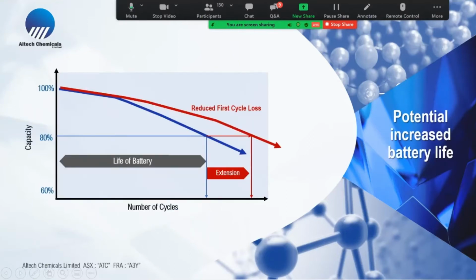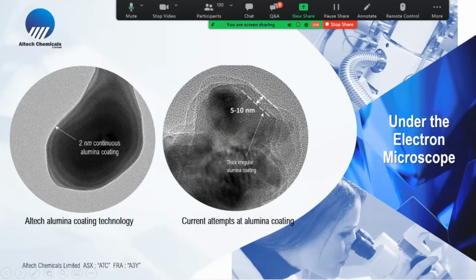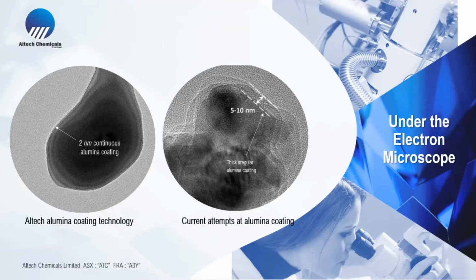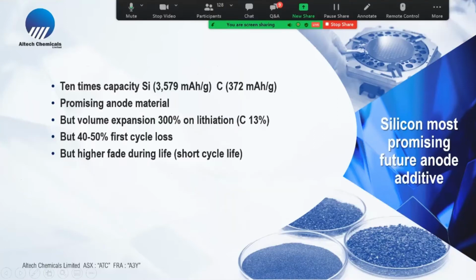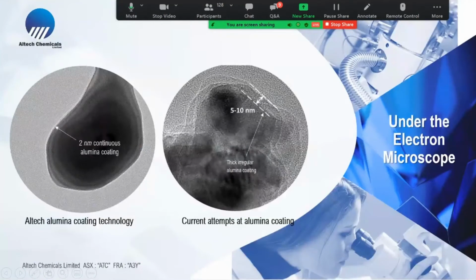And what we're aiming for when we coat the graphite material is an extension of the life of the battery. Essentially, you've got 10% more lithium ions in the battery to use during the life of that. And this is some of our technology under a microscope. On the left-hand side is a graphite particle, and you can see that 2 nanometer thin layer, very efficient technology. As on the right-hand side, this is what the industry is trying to do, very thick, irregular coatings around the graphite. Now let's talk about silicon.